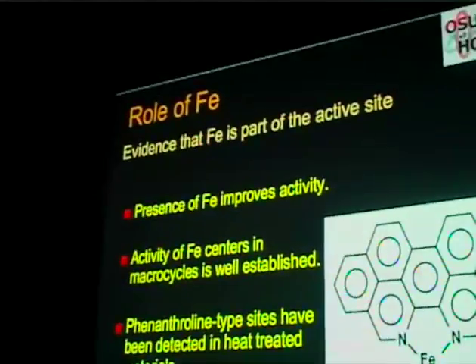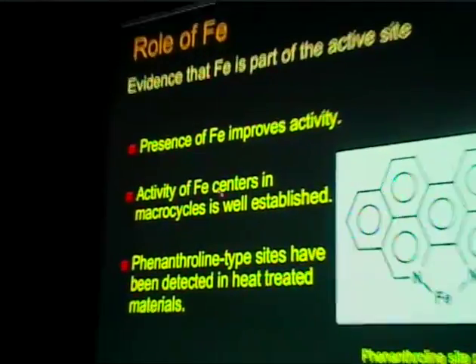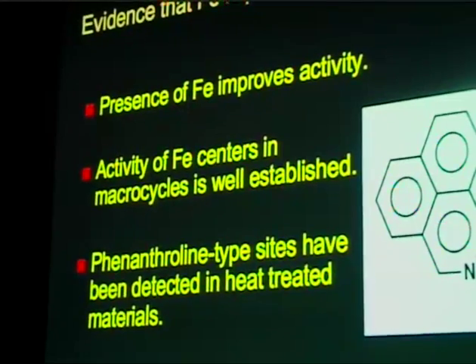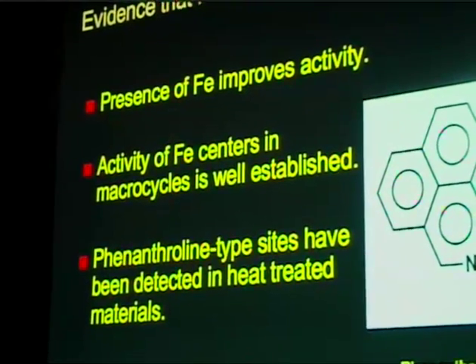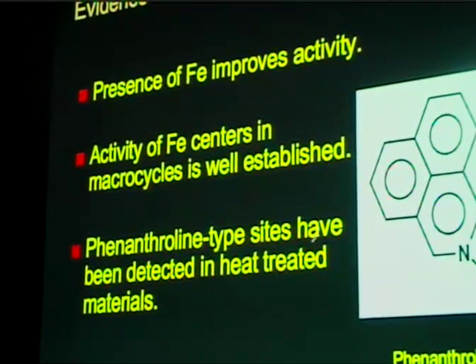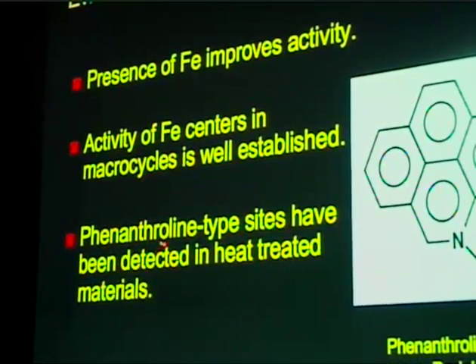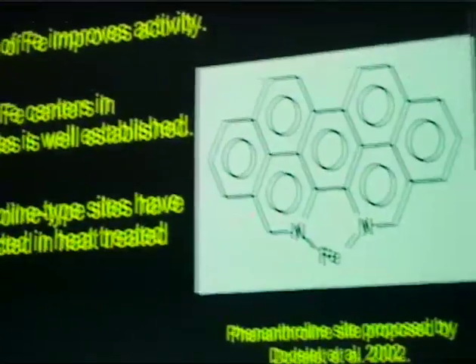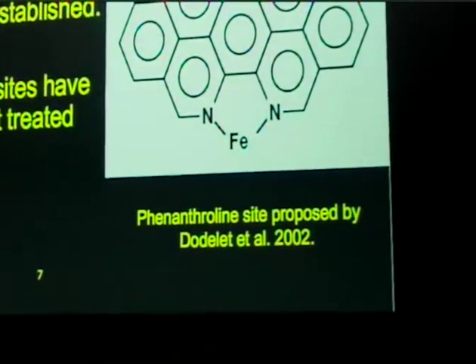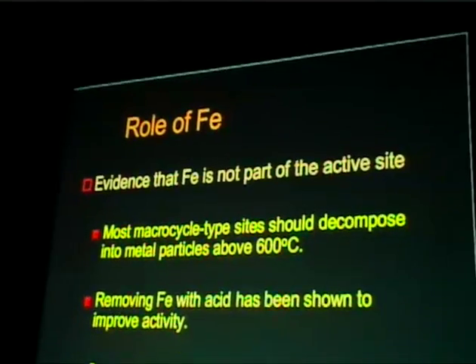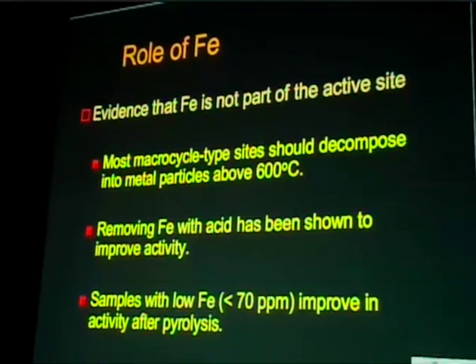that iron is part of the active sites. For example, the activity of iron centers in macrocycles is well established. Presence of iron improves activity. And also some people have reported phenanthroline type sites detected in heat-treated materials. But there's also evidence on the other side that iron is not part of the active sites.